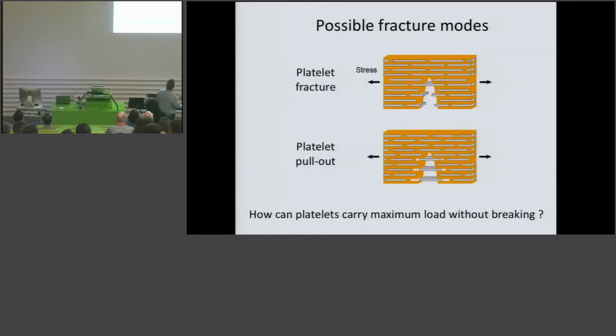And that brings us to these different possible fracture modes, and this is classical composites. It's not something specific to this material, but in general, you do have two situations. In one situation, the stresses that the platelets feel, and these can be rods, fibers, and so on, are just too high and lead to their fracture. They carry a lot of load, but the crack just goes through the material, as opposed to the situation which I just described of pull-out, where you have to pull out the platelet from the surrounding in order to keep propagating your crack.